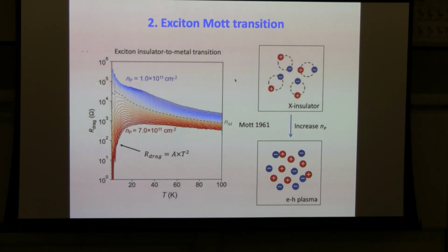And this dashed line is the Mott density. Above that density, you can see that the drag resistance behaves like a metal, with the drag resistance scaling with temperature squared in the high density regime. So that's consistent with this Mott transition picture of increasing the pair density. You go from an insulator behavior into a metal behavior at the critical density, the Mott density. All right. So furthermore, we can extract from this data this constant here, A.